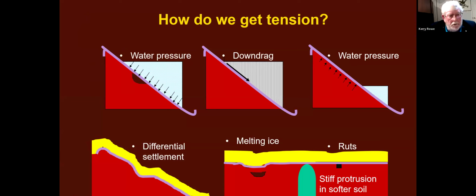You've got down drag when you've got a waste that's consolidating like tailings. You can get water and gas pressures underneath it, differential settlement, melting of ice. Is not perhaps too much of a problem in Australia, but melting of permafrost is a big issue in Canada. If you've got a stiff protrusion and soft materials around it, or even just simple little ruts in the subgrade and you bridge over it, all going to induce tension, which will be particularly problematic if you've got a weld going across it. That is true irrespective of the material, because welds are the weak point.